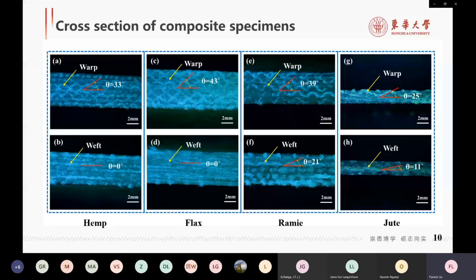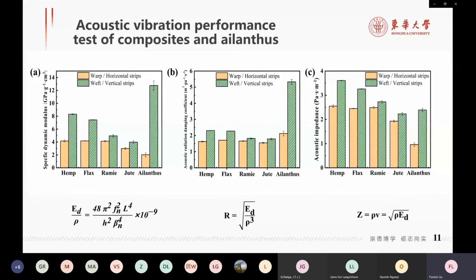The acoustic resistance and the reaction characteristics of a material can be important indicators to evaluate whether it can be used as a tonewood material for musical instruments. The specific dynamic modulus E/rho, acoustic radiation damping coefficient R, and acoustic impedance Z were calculated as shown. The acoustic properties of the four composites were between those of the horizontal strip and the vertical strip of the ailanthus. Since the flexural modulus of the composites was lower than, and their density was higher than, those of ailanthus, their acoustic dynamic moduli and acoustic radiation coefficients were lower, and the acoustic impedance was higher than those of the wood.